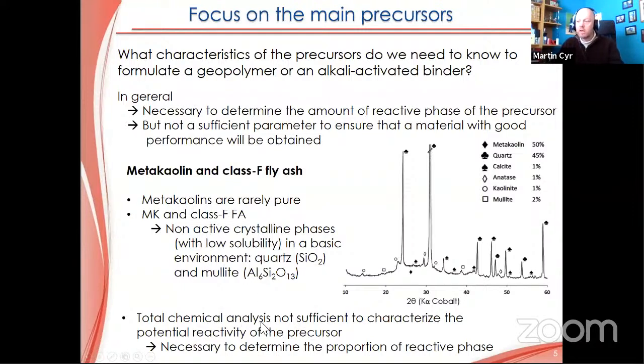So the total chemical analysis is not sufficient to characterize the potential reactivity of this metakaolin, and we need to determine the proportion of reactive phase. There are a lot of papers on that to determine the amount of silicon and aluminum really present inside that could be useful for the geopolymerization or for the reactivity itself.